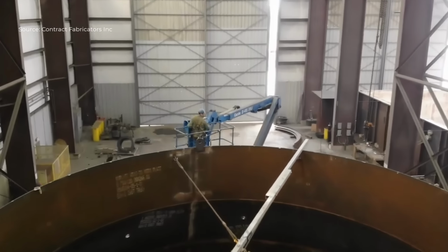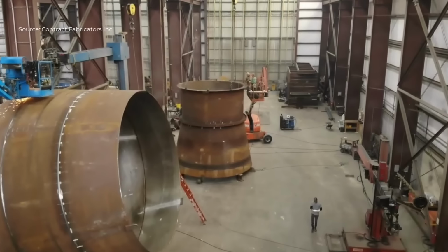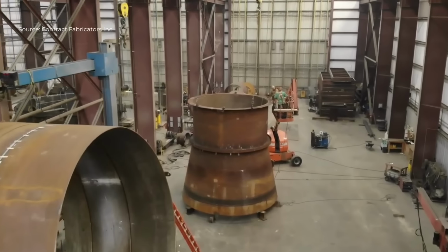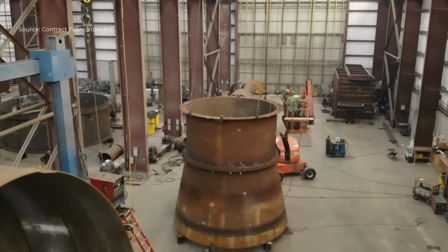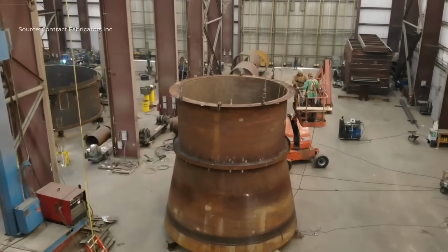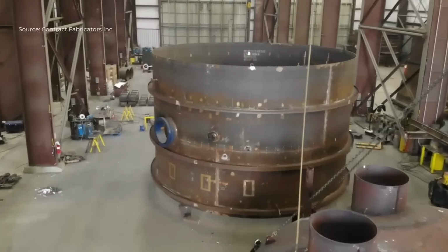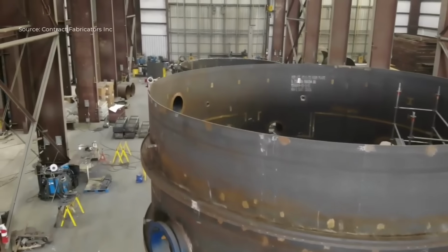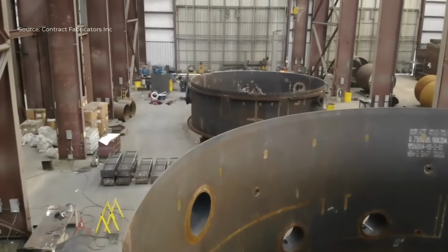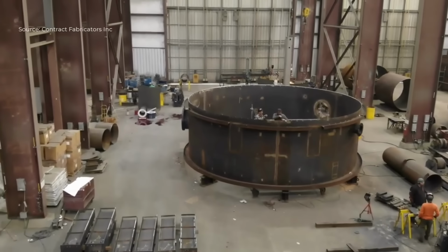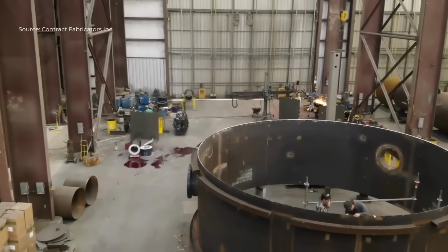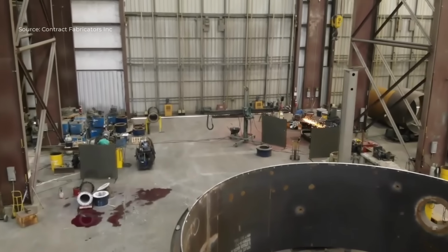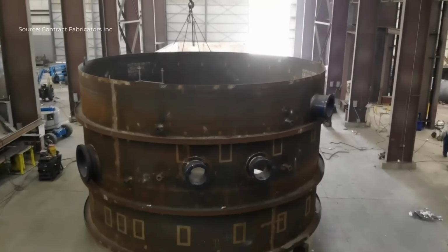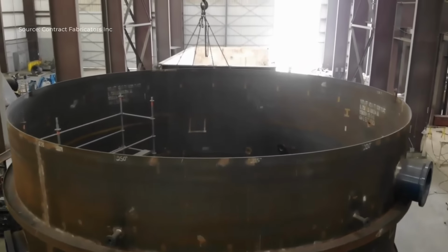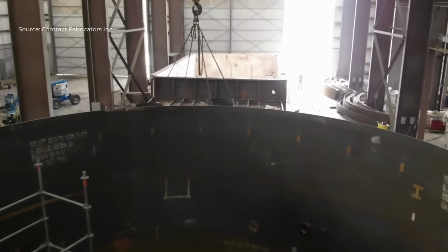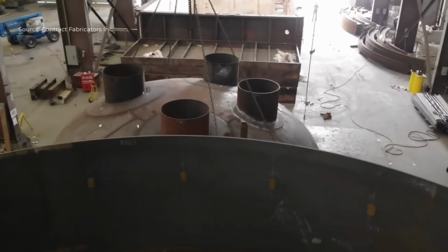A dedicated buffer layer of weld metal is first applied to prevent dilution between the high alloy corrosion-resistant cladding and the carbon steel substrate. After this protective layer is established, additional chemistry layers are deposited, each formulated to match the original clad composition and restore uniform corrosion protection. Depending on project requirements, several welding techniques may be employed during restoration, including SMAW, SAW, ESW, or FCAW, ensuring high-quality fusion and long-term service performance.